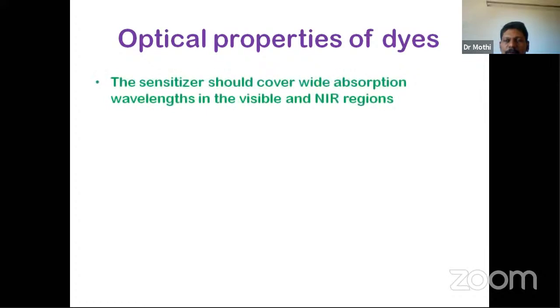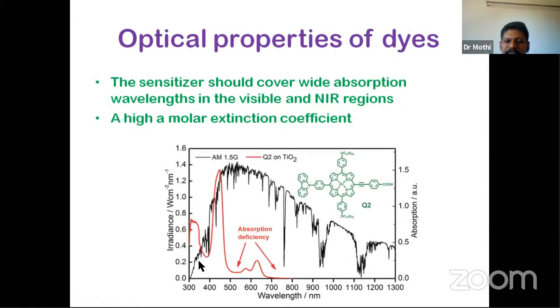What kind of optical properties are required or desired? The sensitizer should cover the wide absorption wavelength in visible and near IR regions. And it also should have a high molar extinction coefficient. That means it should absorb more photons. Right, so here we see a solar spectrum. As you can see here, the sun emits light from 300 nanometer and up to 1300 nanometers. That is from UV light up to IR light.